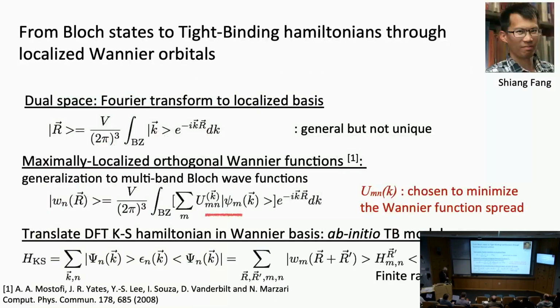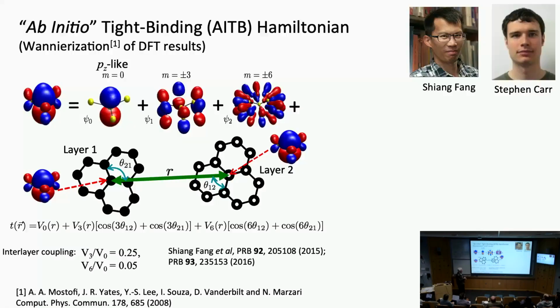Okay, now let's go back to the local Hamiltonian for the electronic states. Again, I'm going to run through this very fast because it's a little bit technical and you don't need the details. Basically, what this slide tells you is I can take the Bloch states, which are eigenstates of the momentum, and with a linear transformation, transform them into localized states, those which are centered around some position in space R. Those are called Wannier states. So this is a simple unitary transformation, and I can impose constraints on that unitary matrix to do the optimal change of basis. So it's essentially a change of basis, and that gives us a local basis which produces the same bands as the extended Bloch states.